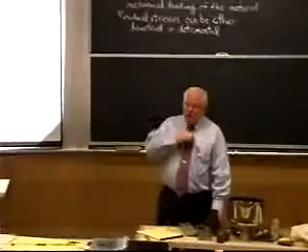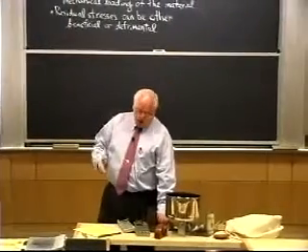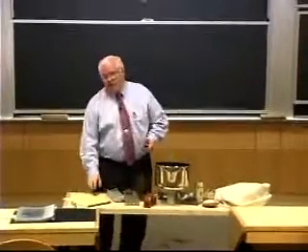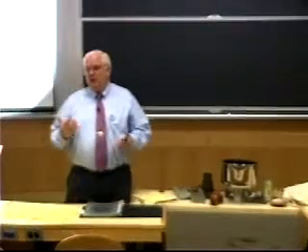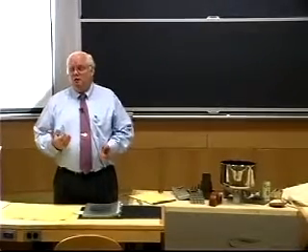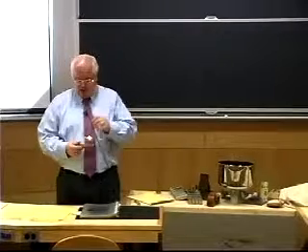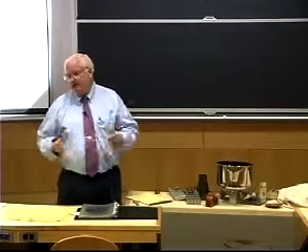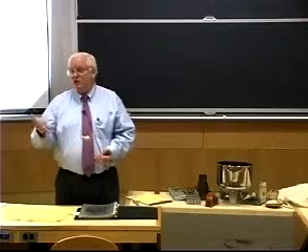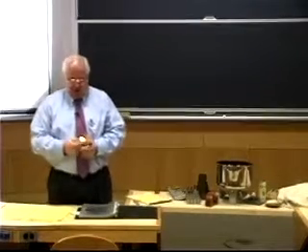We don't use that as much anymore because you have to throw away about 25% of this, or not throw it away, you have to recycle scrap for about 25% of your material. Starting in the mid-60s, people started to do what's called continuous casting of steel. And I don't have a piece of steel that's continuously cast. Actually, virtually any piece of steel was originally continuously cast.